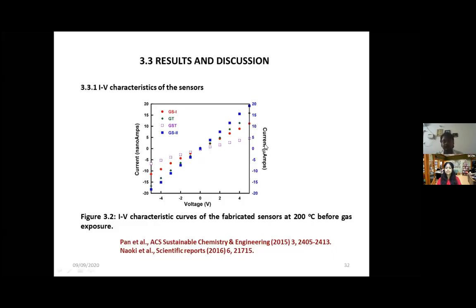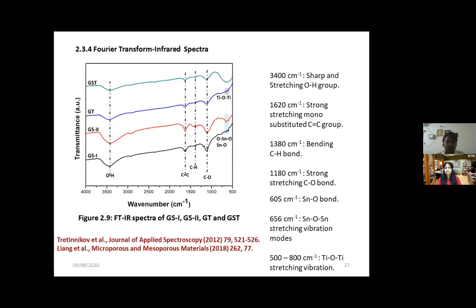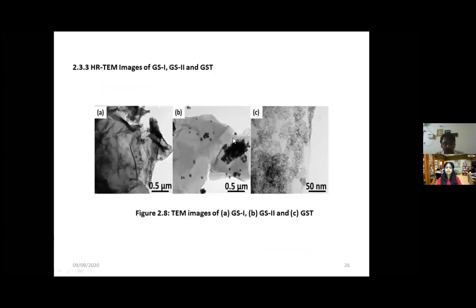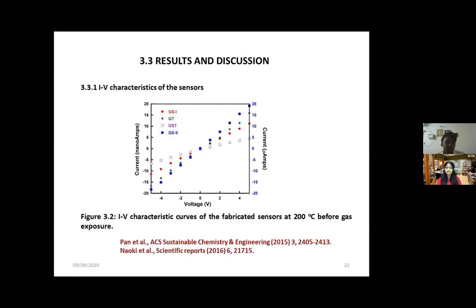So for GS1 we have seen the SnO2 is uniformly distributed. Here it is agglomerated. See, if it is uniformly distributed, there is a heterojunction, that is a graphene tin oxide heterojunction, throughout the sensor material here. However, here the heterojunction is formed only in places, but here there is no heterojunction. So due to the formation of heterojunction throughout the sensor material, there is a barrier. So due to this barrier, there is no flow of charge carriers. And if there is no flow of charge carriers, the resistance is high. So that is the reason for higher resistance in the same material.